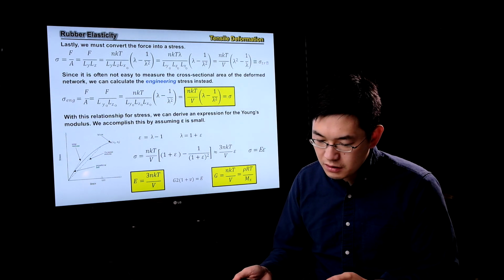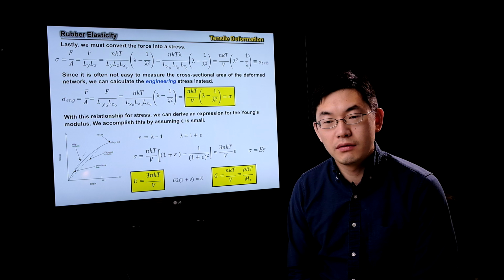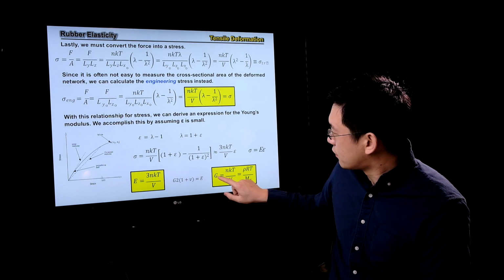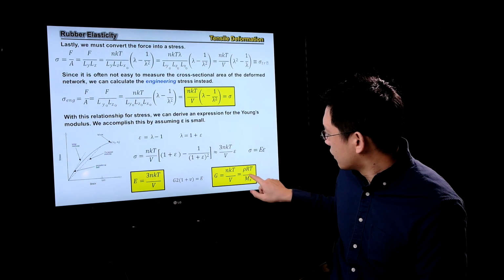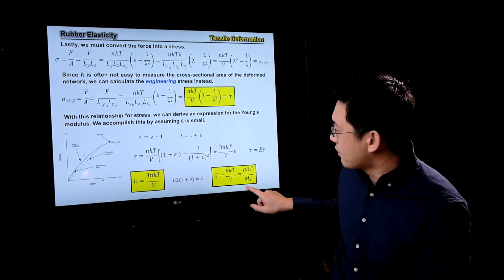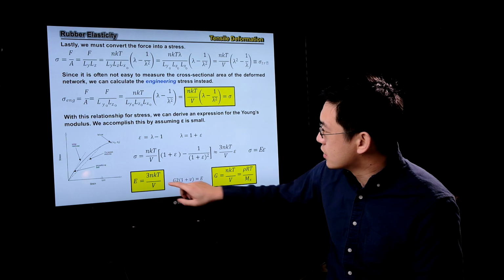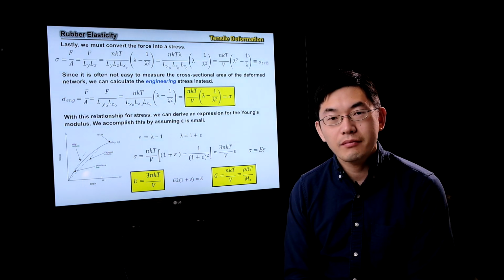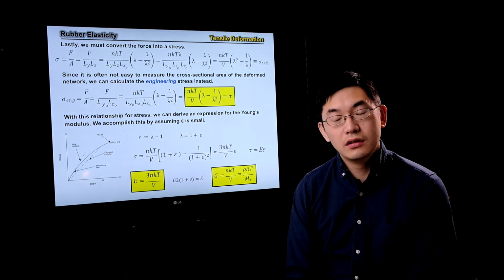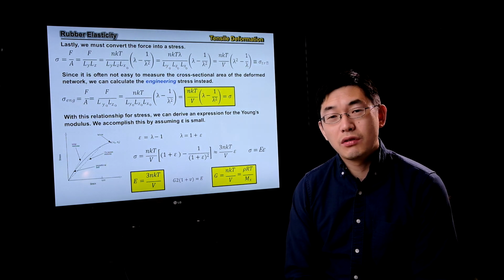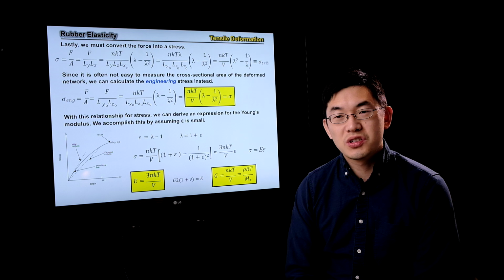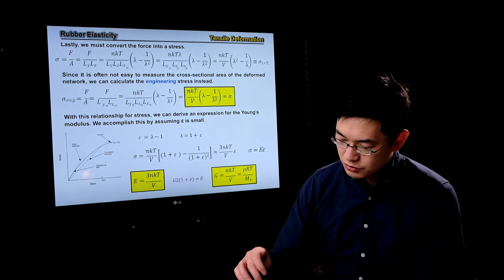So this is where we were left, and this is an important part of the lecture where we discussed what G, the modulus, depends on: the crosslink molecular weight Mc, or you can understand this as the number of crosslink points within a given volume. In other words, the theory nicely describes that if the temperature increases or crosslink density increases, your modulus, or the strength of the rubber, gets stronger.